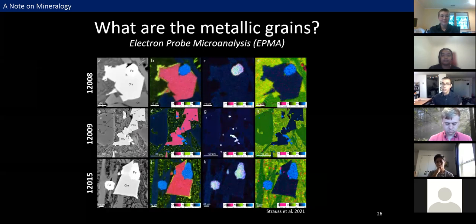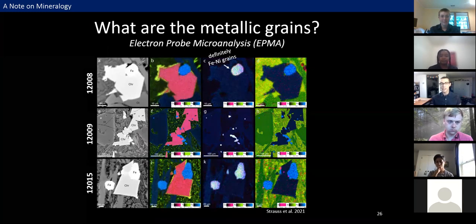The first question we really wanted to answer here was, what are the metallic grains that we turned up during microscopy? So we did some EPMA analyses at Rutgers, and what you're looking at here are qualitative elemental X-ray maps, which we collected in addition to obtaining quantitative points from individual grains. So if we look at the third column, where the background is this dark navy color, I have iron in blue and nickel in green. So we can say fairly confidently that we did find some iron nickel grains, which is very exciting.